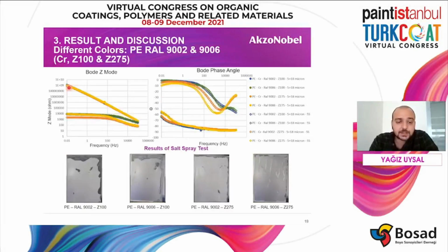We can also analyze the color differences in the samples with chromium pretreatment. Actually, the same comparison can be made with the chromium-free pretreatment. In the electrochemical impedance spectroscopy method, there is no big difference between the metallic gray and the white-gray ones, while there are small differences in the accelerated methods.